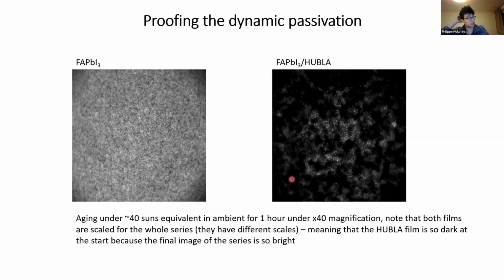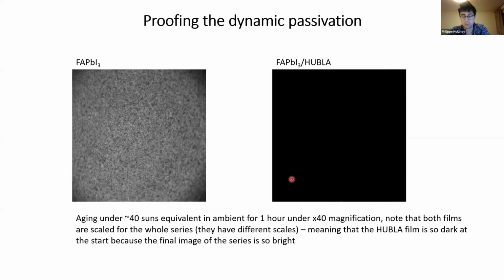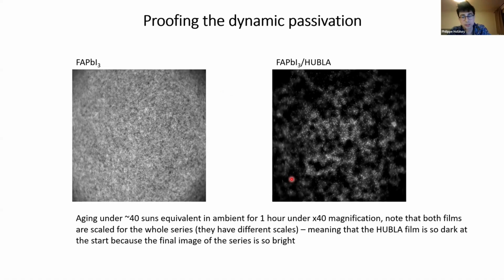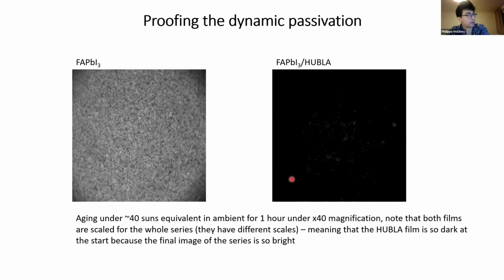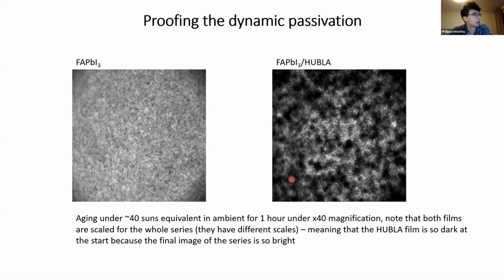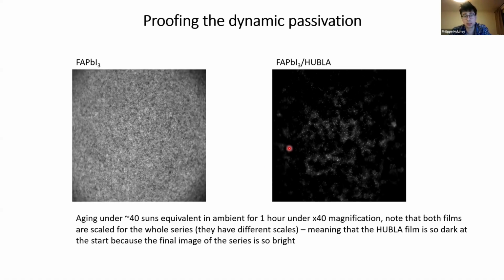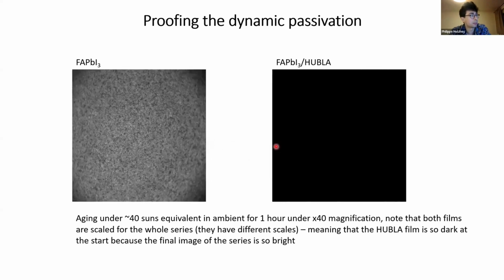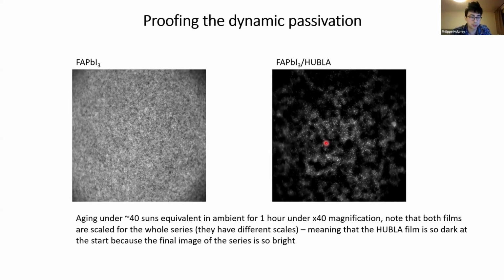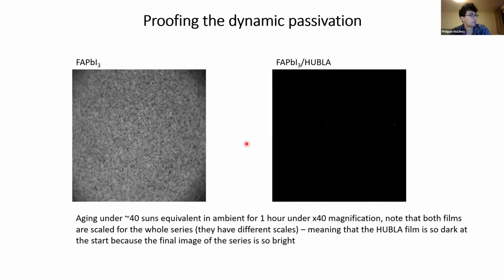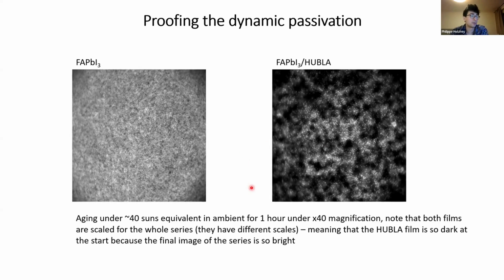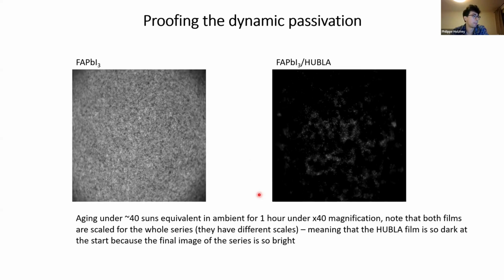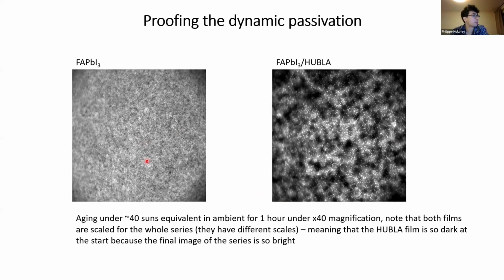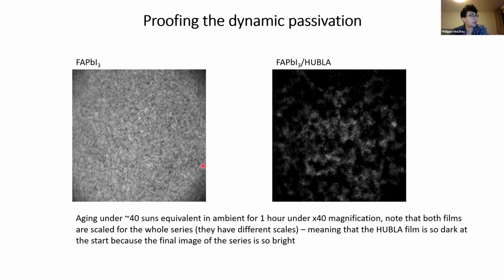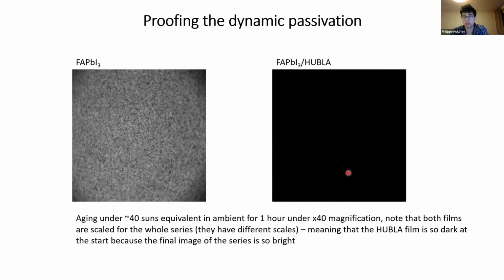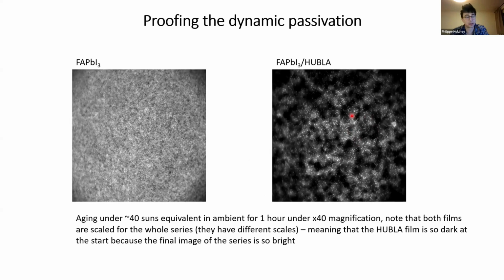Another proof is here. So this is a confocal laser scanning microscopy setup. Or actually it's more of just a PL map really. And those images are not scaled equally, but the left one is scaled differently because the right one gets so bright I had to use different scales. And here we aged the films under 40 suns for 1 hour under 40 times magnification. So you see that FAPI gets a little bit brighter over the 1 hour, but it's really the HUBLA film which improves in brightness a lot over the aging.